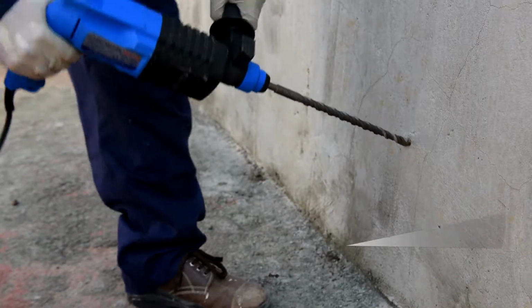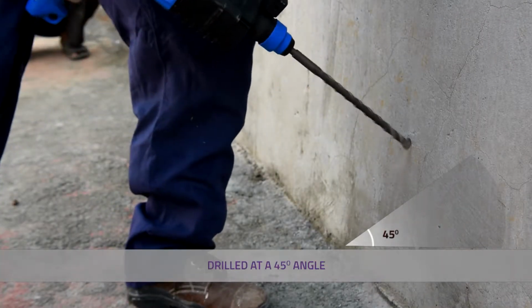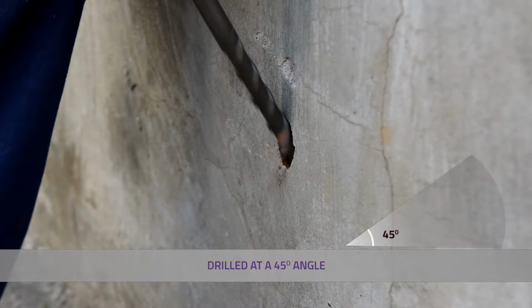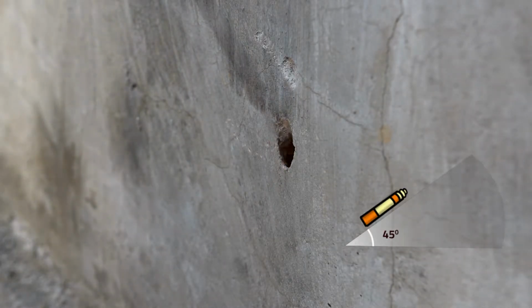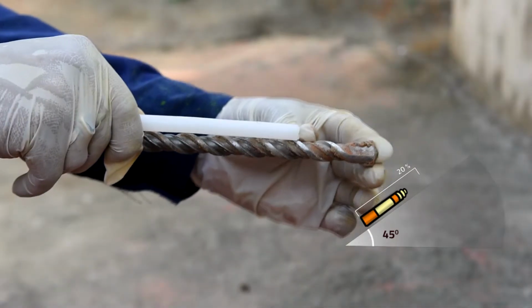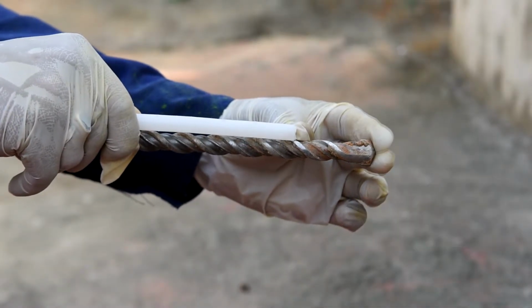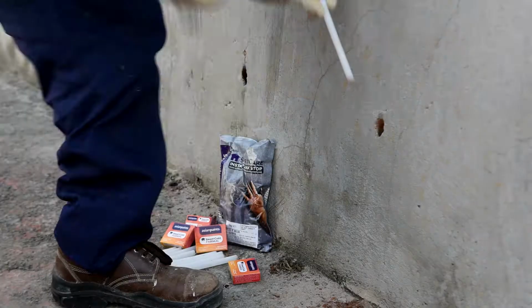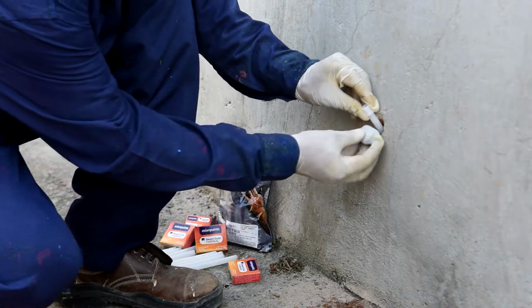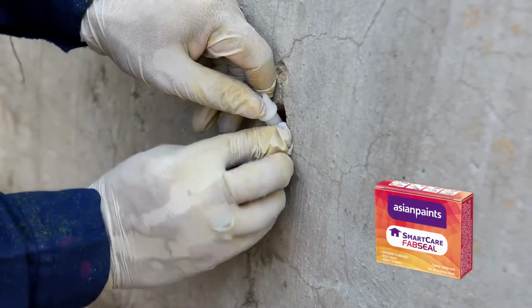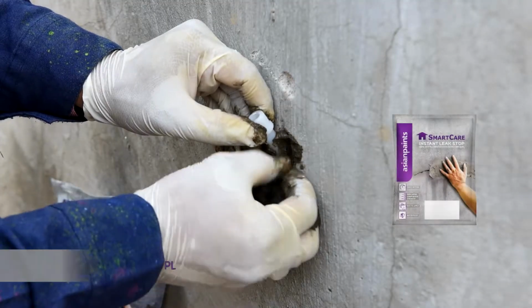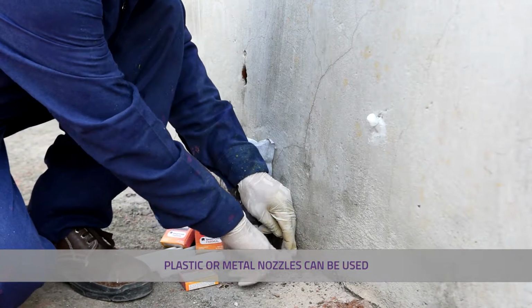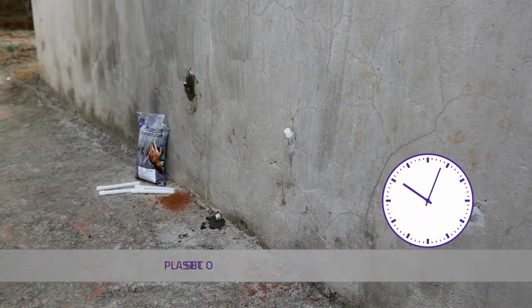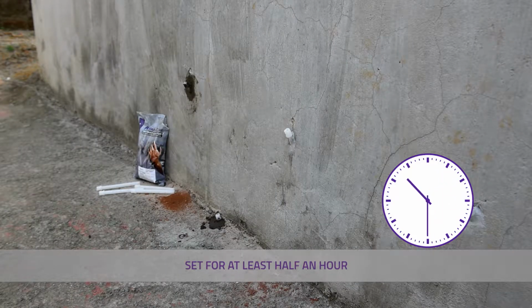The holes for nozzle placement should be drilled at a 45-degree angle. Please keep in mind that the depth of the hole will depend on the length of the nozzle. The drilled hole needs to be 20% more than the length of the nozzle to prevent backflow of material. Once the holes are drilled, the nozzles can be fixed using SmartCare Fab Seal or Instant Leak Stop. Either plastic or metal nozzles can be used. Allow the nozzles to set for at least 30 minutes.